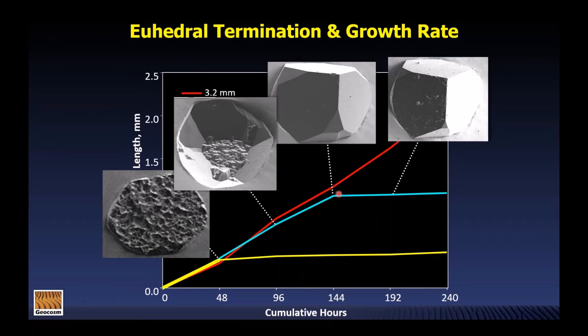So what you can see here is that this inflection point represents the point where the quartz overgrowth first achieves a fully euhedral form. When we are in this fast rate of growth here, notice we have this really irregular, warty looking surface on the top of the crystal, where on the other hand, we have these beautiful euhedral faces that are growing along the sides of the crystal. So what's going on here?